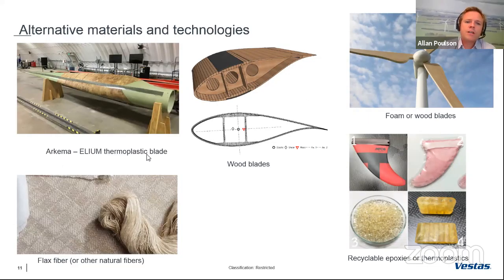Then there is also alternative materials. There is thermoplastic blades, thermoplastics. One of the issues here is that I still need to see that you can get a pure and continuous fiber out from the blades afterwards, and that you can get a higher value out of the resin when it's degraded again after use. Then you also have flax fibers. Here there is potentially an issue with the volume of the fibers.